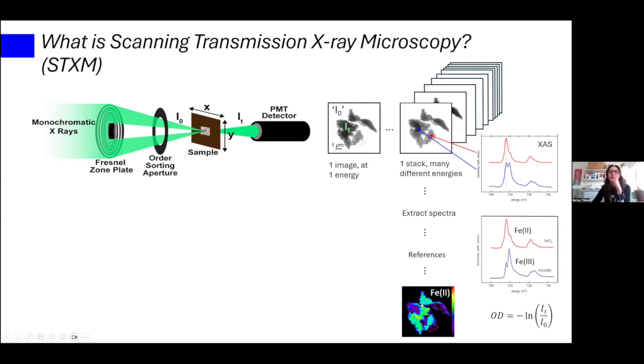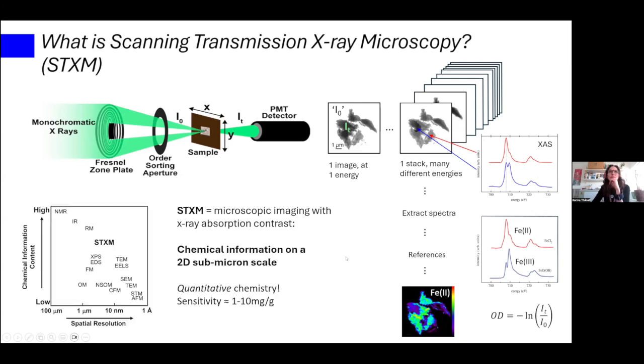In an Fe3+ image, these areas would maybe be more lit up. And what is represented here, as you can see, is sort of the opposite of what we have here, right? What is here white, because there was no absorption, is now black. And that is because what we typically plot is this quantity, the optical density, calculated in this way from the original images. So this is basically what STXM can do for you. It is microscopic imaging with X-ray absorption contrast.